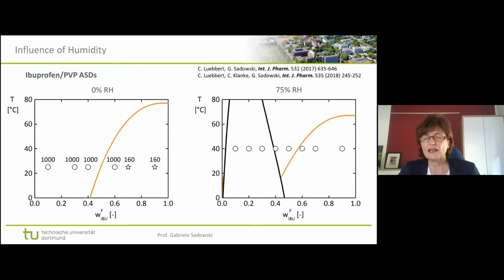And again, we have prepared our formulations. We stored them at 40 degrees centigrade because this is the temperature that belongs to 75% relative humidity. And then we can see what we expected. So these three samples to the very right, they are right of the solubility line, so we expect them to crystallize. All the others are left of the solubility line, so we did not expect any of those to crystallize.